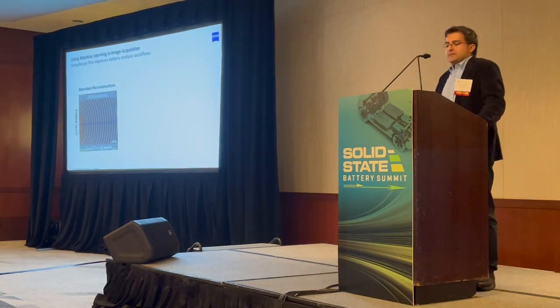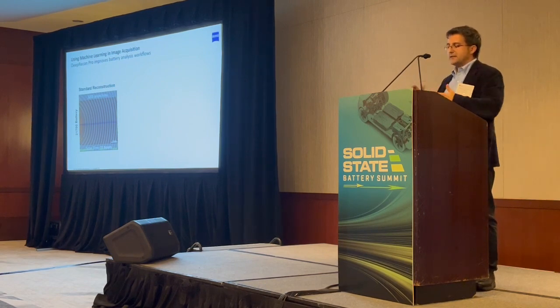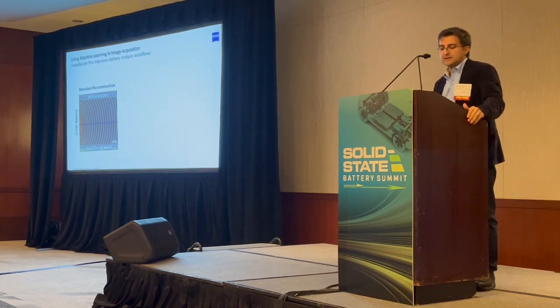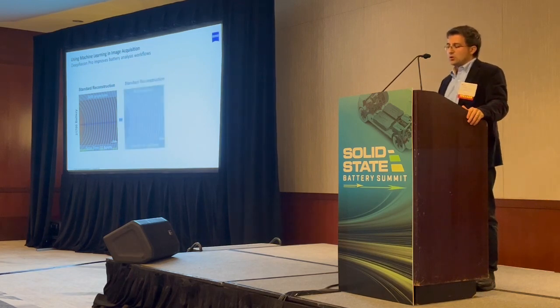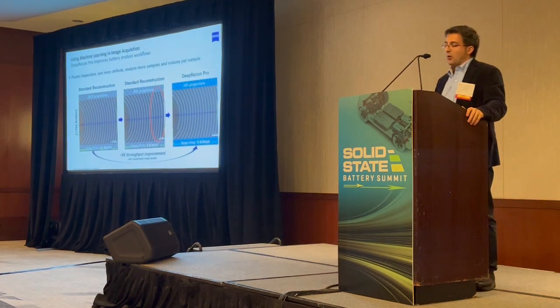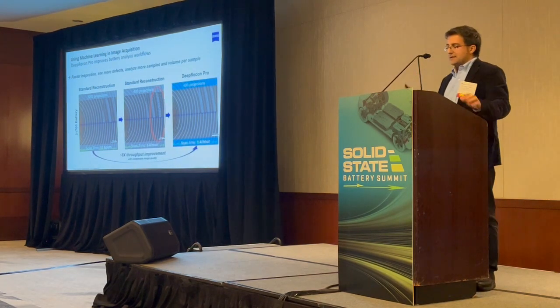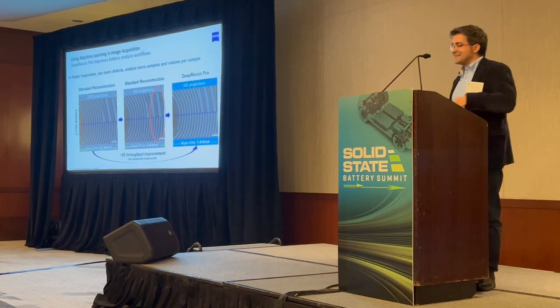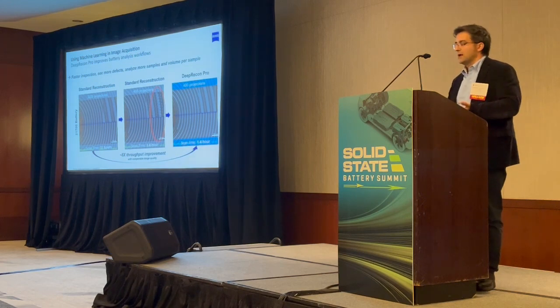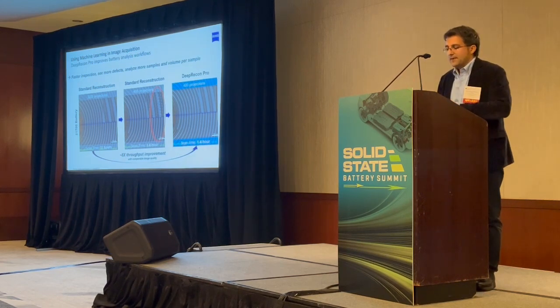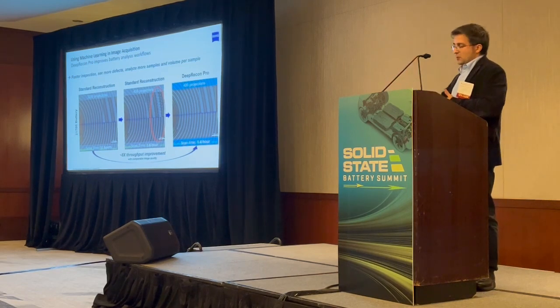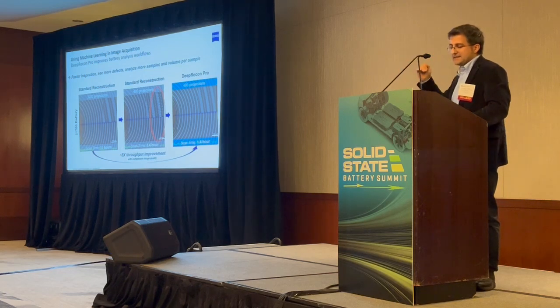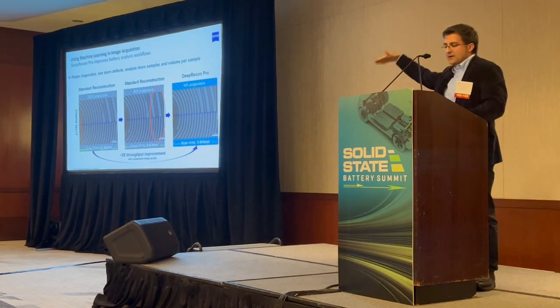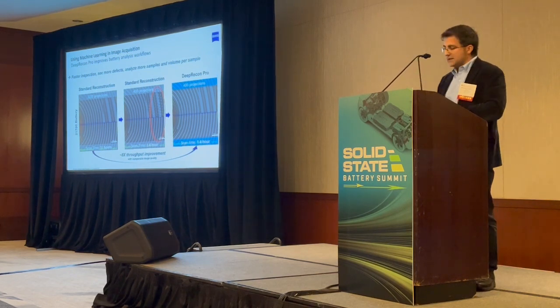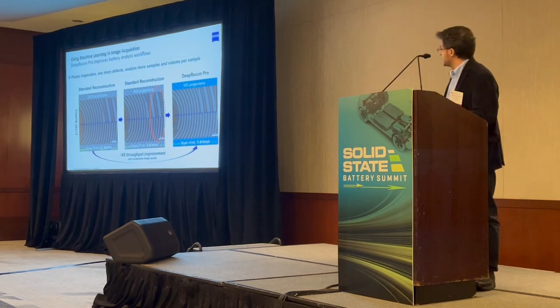For other types of repetitive tasks, like measuring layer thickness and inspecting the whole battery, or maybe large battery cells for large defects, like in this one, which is a 21700 cylindrical cell, we could go from 3200 projections to 400 projections. And you can see that if we use the traditional algorithm, significant artifacts will appear. Those artifacts are called aliasing or undersampling. But if you use the deep training network, or DeepRecon, then you can remove those artifacts and provide equivalent results in 1/8 of the time of the first image, which will take around 11 hours. So you can reduce the time to 1.4 hours.